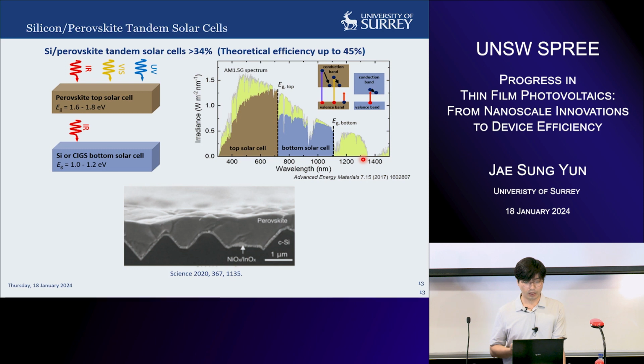Another point I wanted to make is that perovskite solar cells are a band gap tunable material, so you can change the band gap by using different compositions. I think people are familiar with the tandem concept, where we can put a high band gap material on top of silicon. So we can have a band gap around 1.6 to 1.8 eV, and we can collect a wider spectrum of the light. And there has been a lot of great progress. Now people are able to deposit a perovskite layer conformally on top of the textured silicon surface as well.